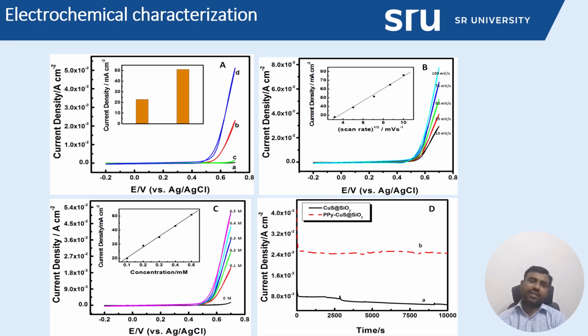Further, the concentration effect is another important parameter, because when developing any catalyst, it should work over a wide range of concentrations from low to high. Hence, we have used the same cyclic voltammetry measurement to confirm whether increasing the concentration affects the catalytic performance of our fabricated catalyst. Initially, for the PPY copper sulfide hybrid electrode modified glassy carbon electrode, we recorded a CV without any addition of methanol. After that, we added methanol sequentially, for example 0.1 molar, 0.2, 0.3, 0.4 and 0.5 molar methanol in 0.1 molar NaOH solution.